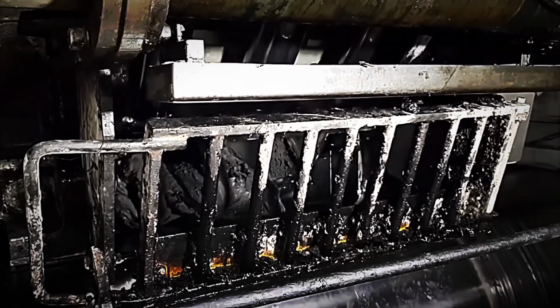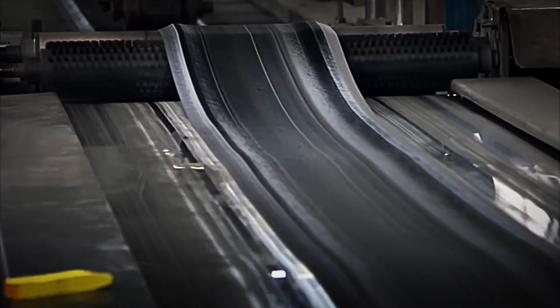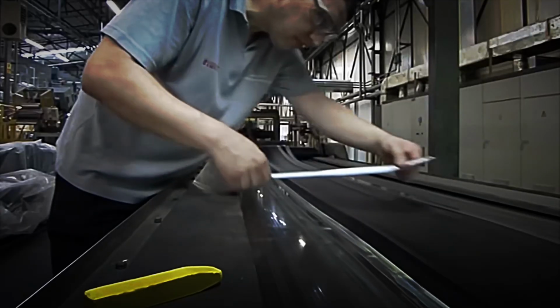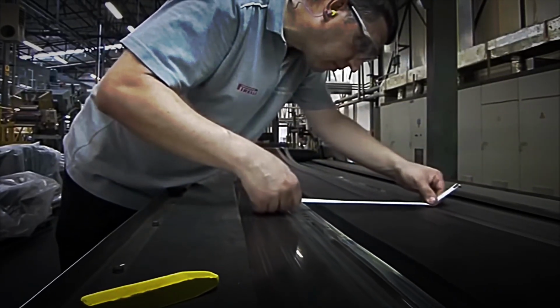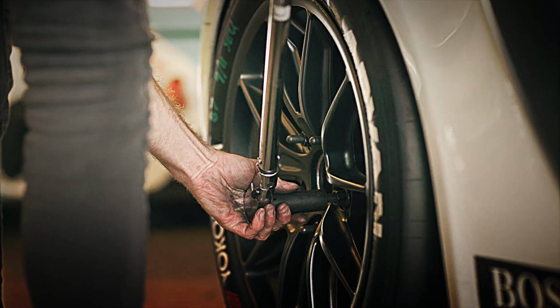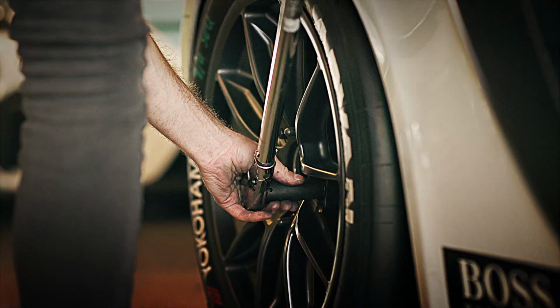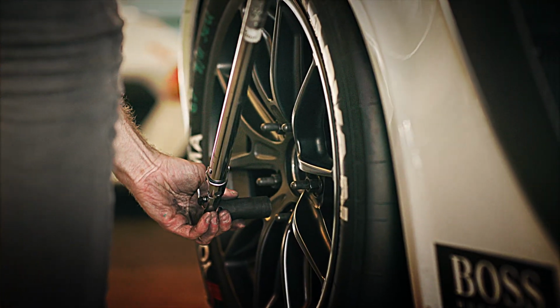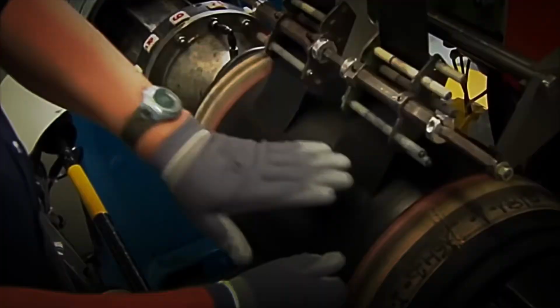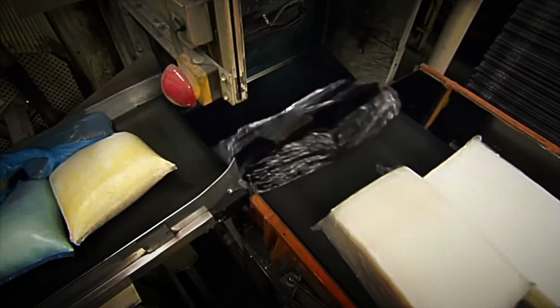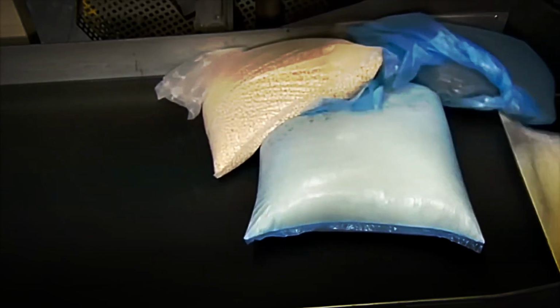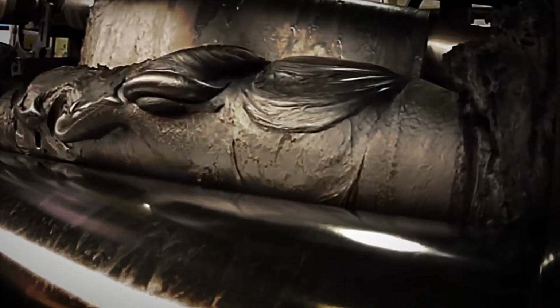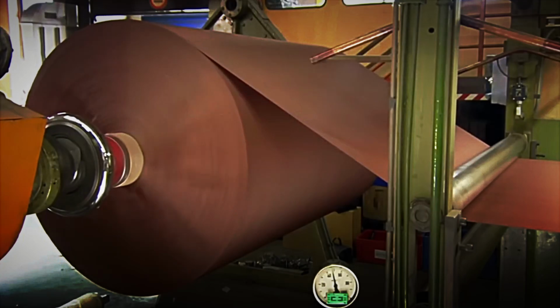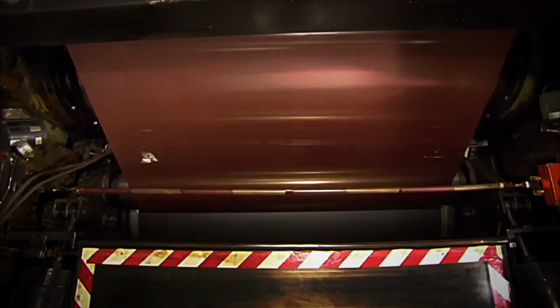The green tire then enters a steel mold split like a giant waffle iron. Inside sits a flexible bladder of water and steam. When the mold closes, pressure, which can top 20 atmospheres, and temperature around 180 degrees Celsius, activate the sulfur and create sulfur bridges between polymer chains. After roughly 15 minutes, the tread gains its final pattern, and all layers bond chemically into a single elastic, solid, highly durable piece. Excess rubber, or flash, is trimmed with circular knives.